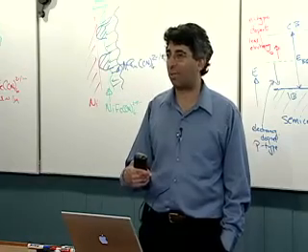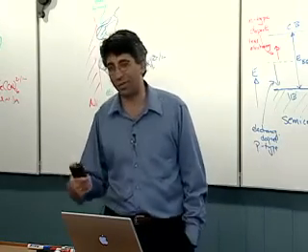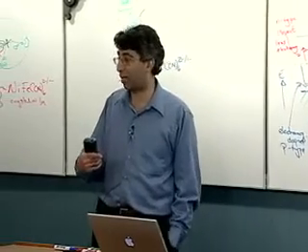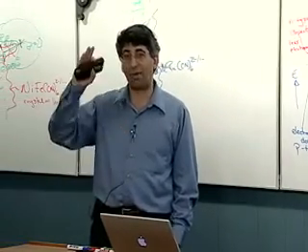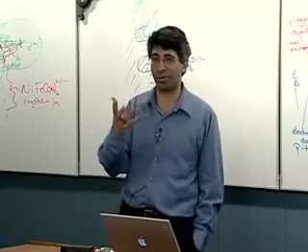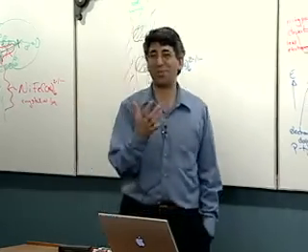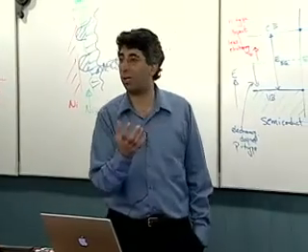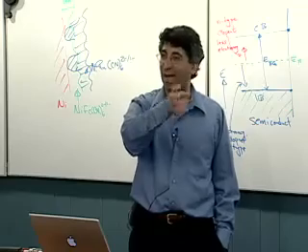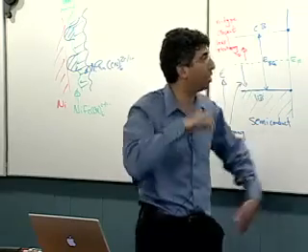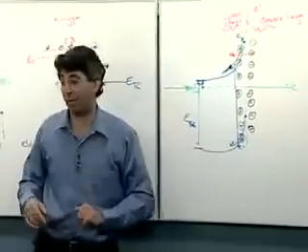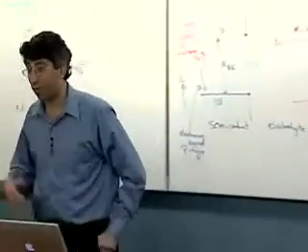So perhaps the most successful cell, not perhaps, clearly the most successful cell is the so-called Gratzel cell, which is a TiO2-based cell. And to get around the fact that it's wide band gap, Michael Gratzel, I guess, adsorbs a ruthenium-based dye on the surface of the TiO2, and the light is absorbed into the dye. The dye injects charge into the semiconductor, and we take advantage then of the band bending to keep the charge from recombining. But in doing that, we're no longer splitting water.